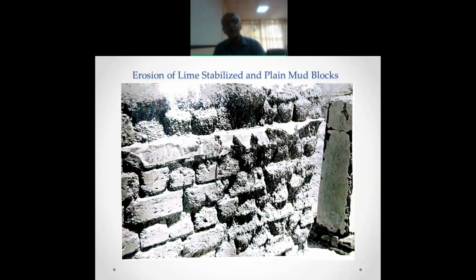Here is an experimental wall I built with lime stabilization, 5% lime stabilization on the left side, plain mud on the right side. After 2 or 3 years, I took this photograph. You can see the plain mud has eroded, the corners have gone. But the lime stabilized blocks are absolutely good, the surface is not eroded. So it shows the value of lime stabilization. Lime stabilization may not increase the strength enormously, but it will prevent erosion.